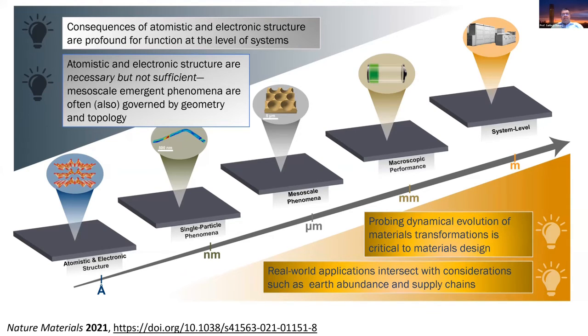Without protein crystal structures, people were still doing a lot of work, but a lot of it was indirect, right? And so in the case of cathode design, there's still a lot of very good modeling going on that allows you to get insight into atomic diffusion pathways, but it's really been very difficult to really know what is happening at the atomic level in terms of the pathways adopted by ions. So single crystals, I think, fill that urgent need to know how the structure changes and where exactly the lithium ions sit inside the structure, and how they migrate through.